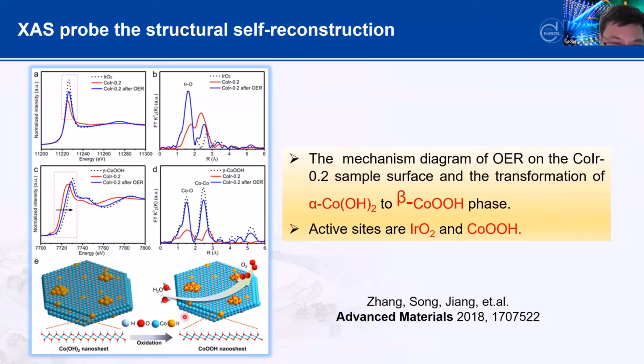Basically, as you can see, the structure is like this. In some cases, this is in-situ synthesis. During synthesis, we put iridium with this precursor, and during the layer formation, we will have some very tiny iridium atoms and also iridium clusters, which are really trapped in this lattice. During the reaction, in most cases, the cobalt hydroxide will be changed to the oxide because of the electrolyte. That means the cobalt will be oxidized, especially on the surface. But meanwhile, because the iridium is also located at the surface, as you can see here, it also changes by being oxidized. So that is what we understand here.